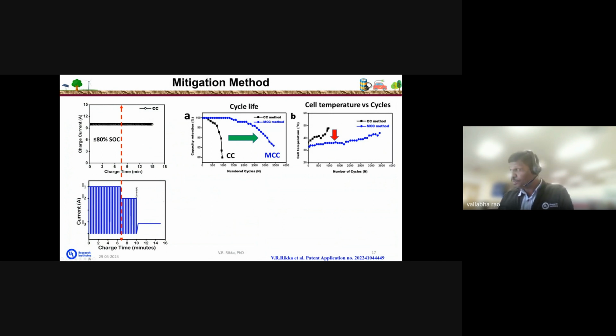charge mechanisms. So this test protocol clearly indicates that when we decrease the current pulse at the end of the cell voltage, it can reduce the overall cell temperature rise by minimizing the internal cell resistance, and it allows the utilization of the active material from the cathode as well as from the anode during the discharge process, which can enhance the cycle life. That's how we have implemented this test method to improve the cycle life.